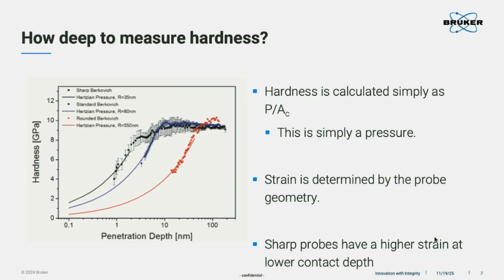For the larger tip, the stabilized zone is close to 100 nanometers. It comes later, because the tip is blunt, so you get the plastic deformation later. So selecting the probe is also very important. If you want to get a shallow indent, you need a sharper probe, and you can get the hardness value in a very shallow area, right? This also influences our mechanical mapping pitch.